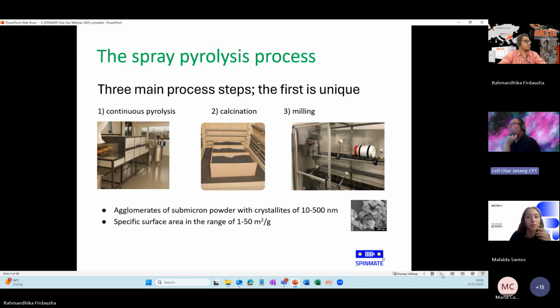Yeah, so spray pyrolysis, which is our production method for mixed oxides, consists of a pyrolysis step, which is a continuous process, then calcination, which we currently do in crucibles in chamber furnaces, and milling and sieving, and usually also a second thermal treatment to remove any residual mill jar or other organics that might have entered the powder during processing.